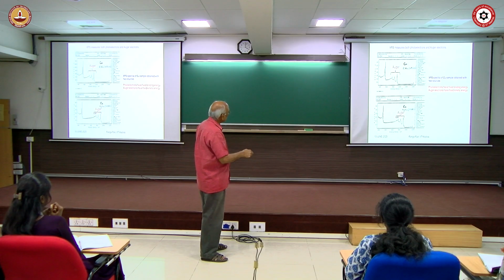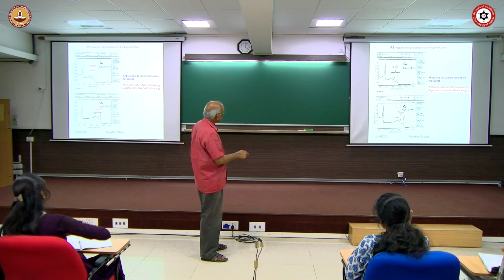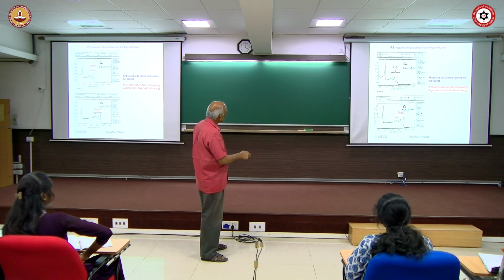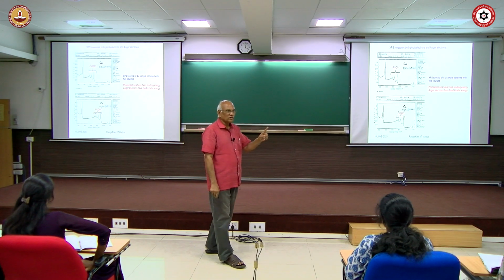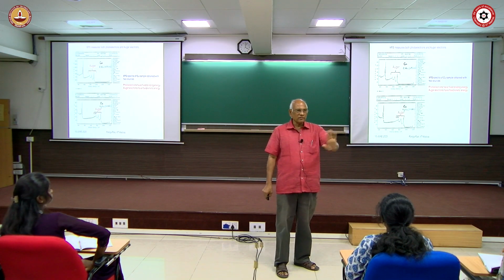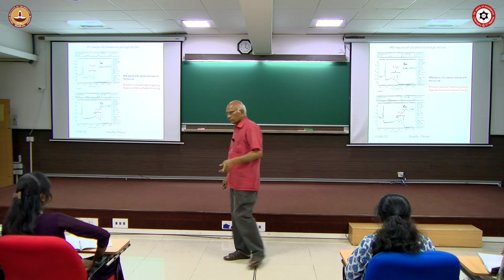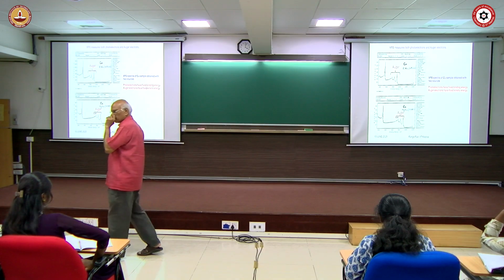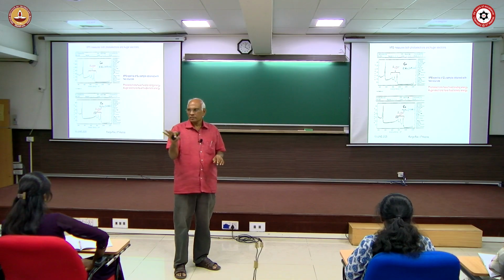Whereas the copper 2p level comes here at around 500, and here at 300. So hν is different and the kinetic energy changes, whereas the Auger electron kinetic energy does not change. This is a proof. All of you got this point or not? Okay, good.